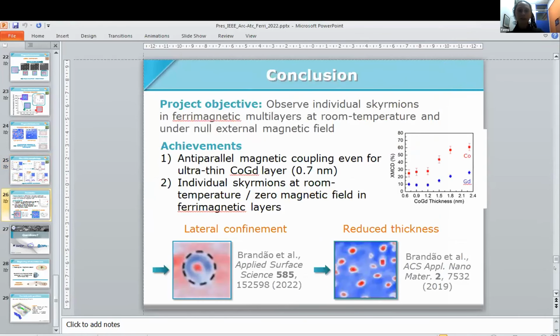So in conclusion, the objective of the project was to directly observe individual skyrmions in ferrimagnetic multilayers at room temperature and down to zero external magnetic field. What we achieved here, first, was to prove that we have an anti-parallel magnetic coupling even for ultra-thin cobalt gadolinium layers, down to 0.7 nanometer: cobalt gadolinium is a ferrimagnetic host.